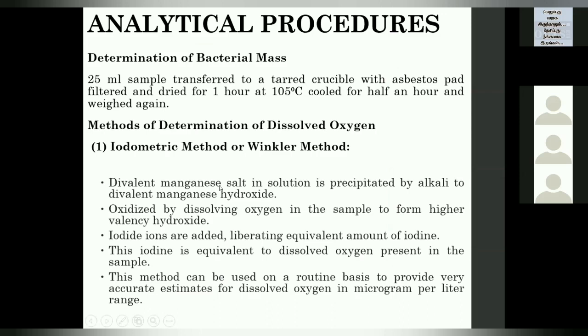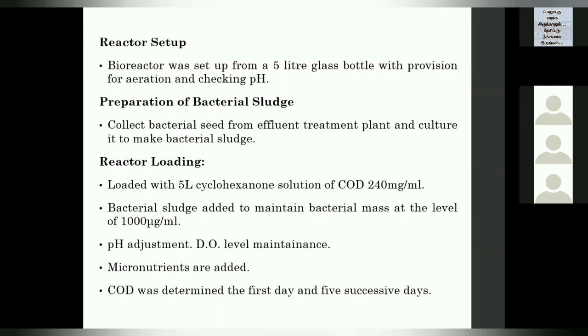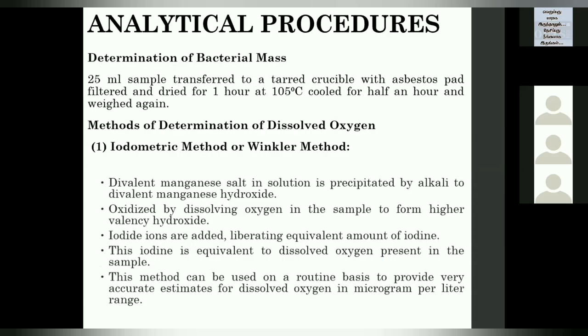Then for the preparation of bacterial sludge, we had to make it to 1000 μg per ml concentration, and pH was adjusted to 6.8. DO level was maintained at 5 μg per ml. Micronutrients like phosphate buffer, calcium, magnesium, all that was added, and COD was first determined on the first day and then followed by the successive 5 days.